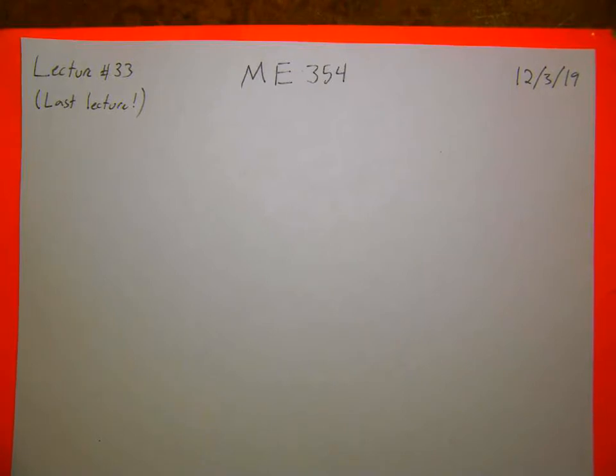But now as we get into higher strains, basically this region immediately starts plastically deforming. So you see now this is at 9 seconds. This max is 0.45. At the next step, this is 0.75. At the step after that, this is 1.1. So it's just ramping up very, very quickly, much higher than the far field applied strain is. And that's because here we have plastic deformation localizing.